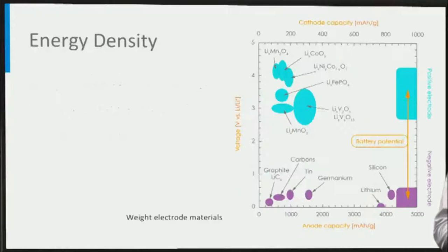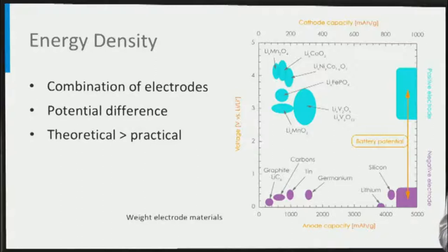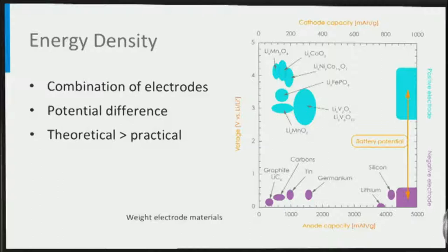The approach of calculating the electrode capacities and the battery energy density is as follows. Imagine we need to store one mole of lithium ions — then the capacity equals Faraday's constant, approximately 96,500 Coulombs. To store this capacity in a lithium-ion battery we can determine the amount of moles of electrode materials from the redox reactions, and from this their mass. The capacity divided by the weight of the electrode is the specific capacity. Because the anode and cathode generally have a different specific capacity, the masses of the anode and cathode will be different.